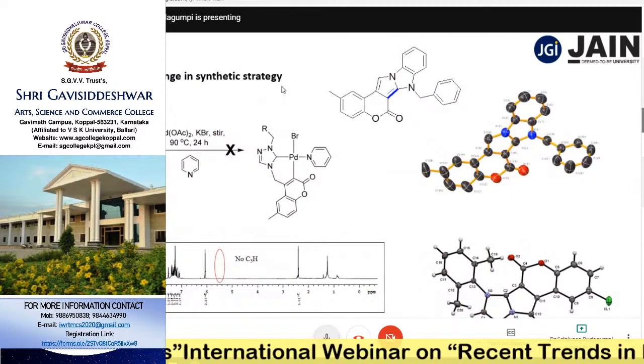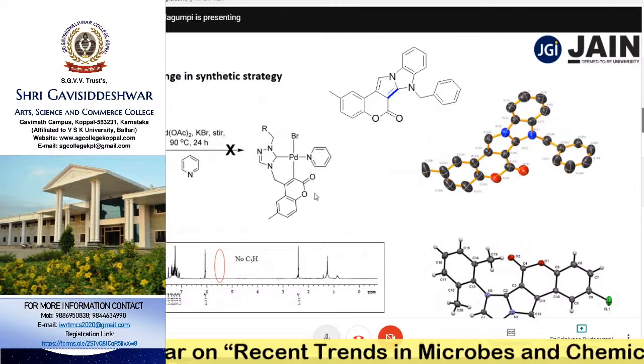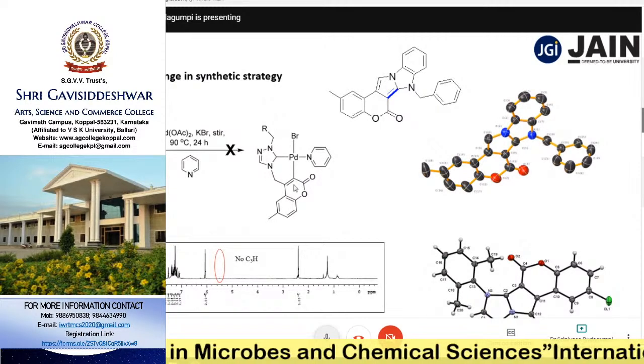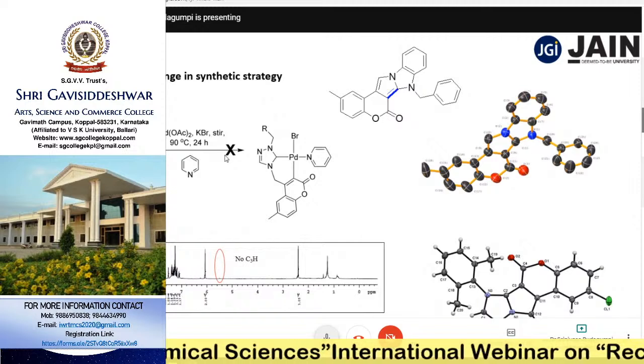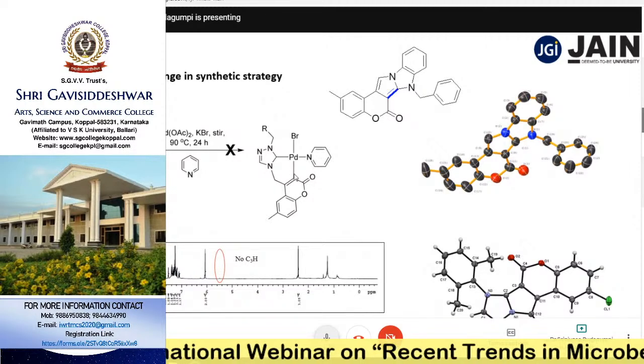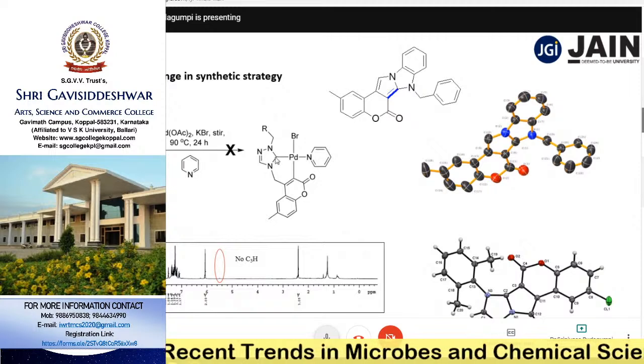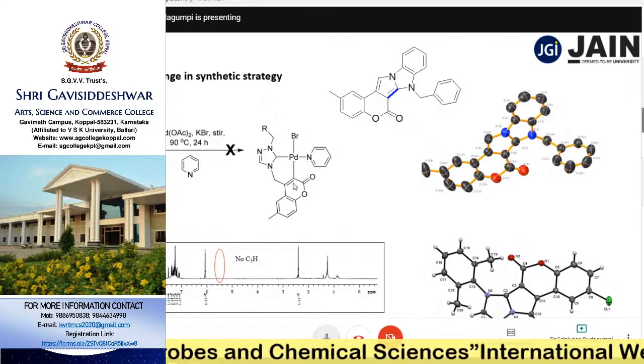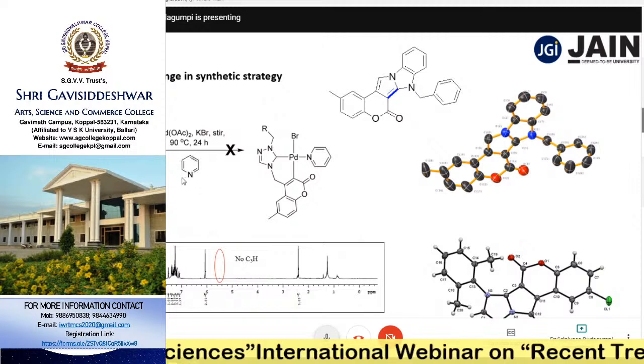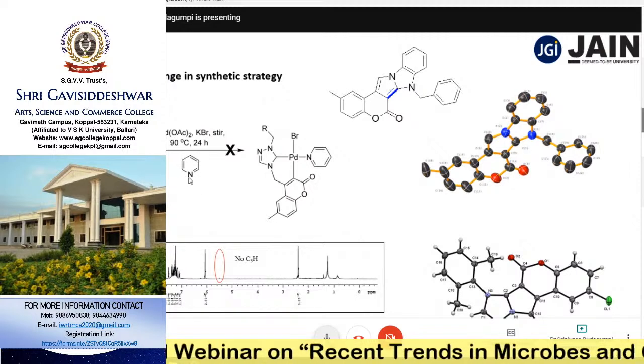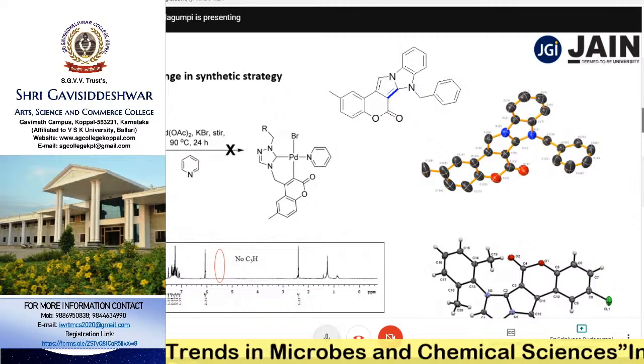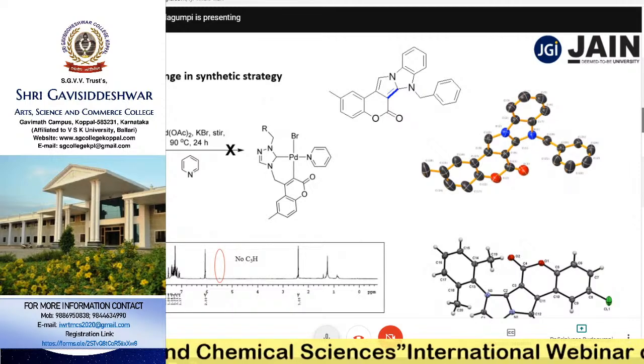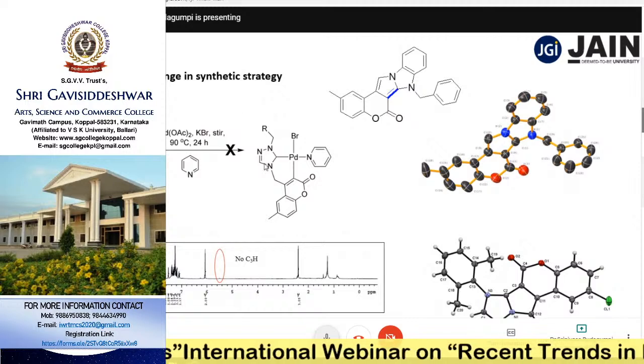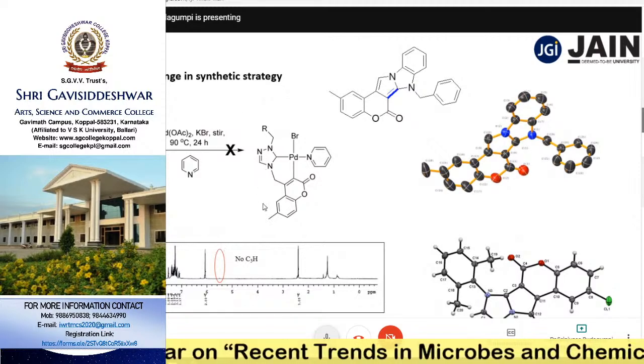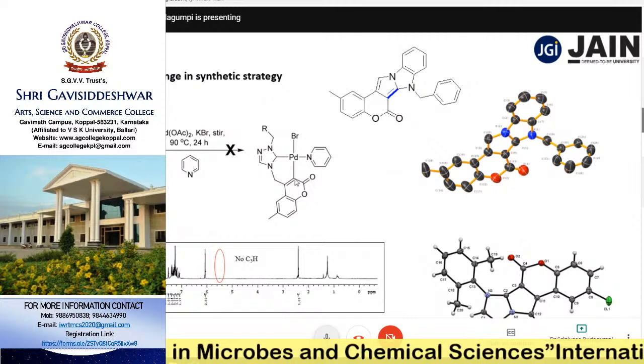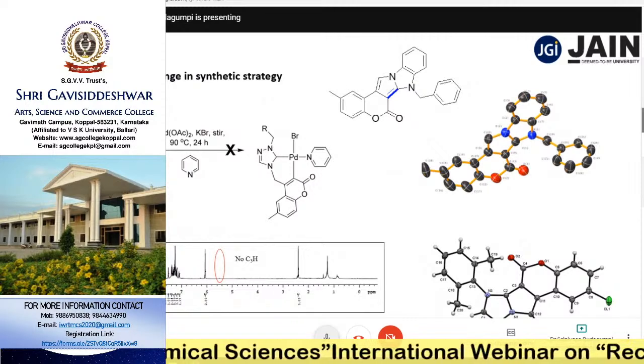Further, we changed the strategy to get what we intended, this kind of complex formation, but that was not possible again. But we got a product which is not having the C3 proton, nor the C5 proton. So what is the change in the synthetic strategy now? The reaction was carried out in pyridine. We thought that pyridine is sufficient to deprotonate the C3 proton of coumarin and the C5 proton of triazole. The product we got, we analyzed by proton NMR, and proton NMR says that there is no peak corresponding to C3 of coumarin and no peak corresponding to C5 of triazole.